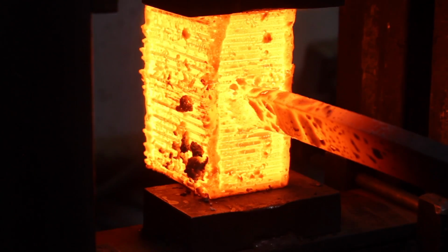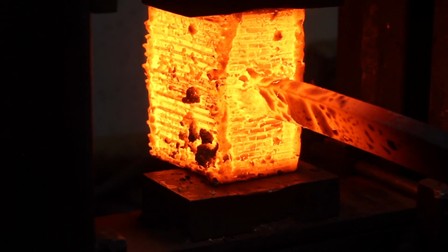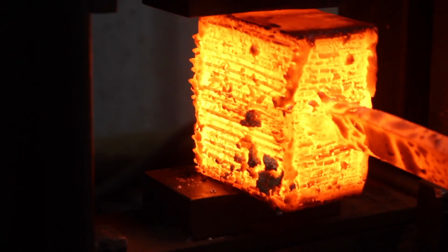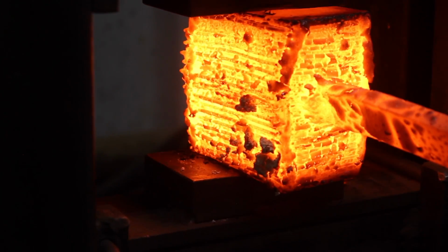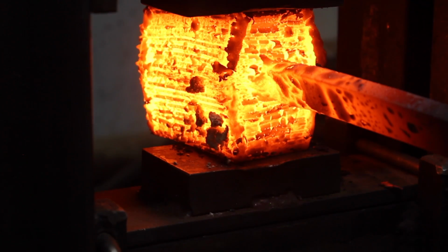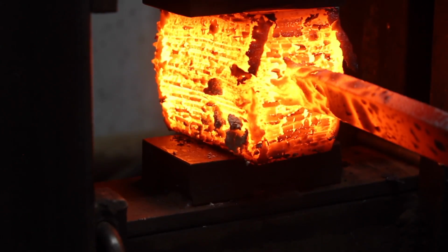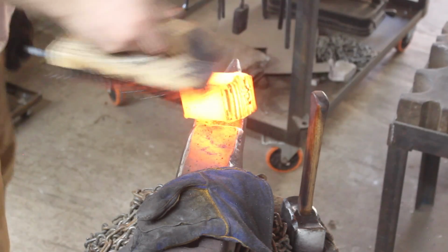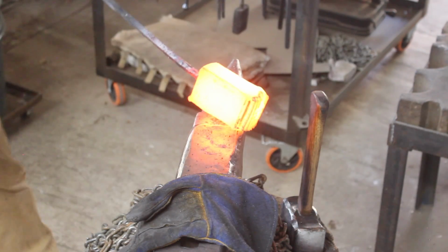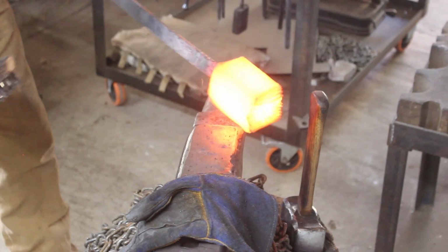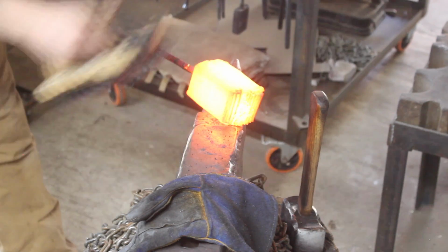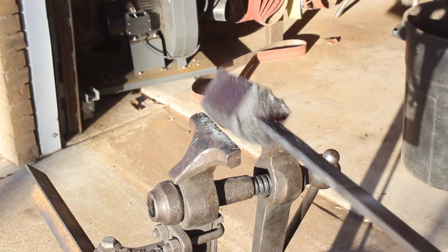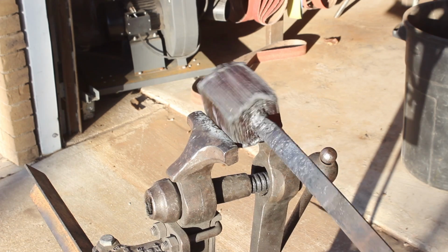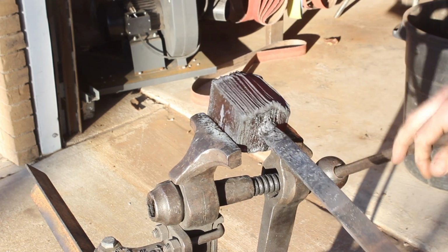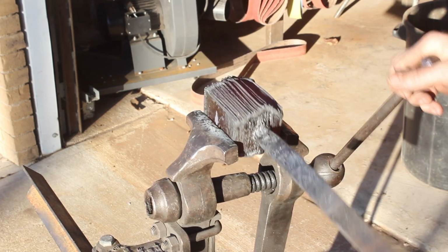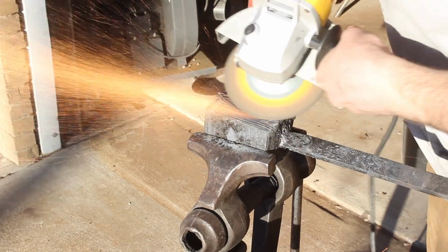And once we've packed the billet a little bit and then brought it up to final forge welding heat, we can go ahead and complete the forge weld in the press here, as you can see. And you notice that I didn't put the whole thing under the dies and just press straight down, but I worked it from end to end, and that allows any flux or impurities to be forced out the other end as you work it forward or backward, as the case may be, and helps preclude any inclusions or pockets that could potentially form if you just press straight down immediately.